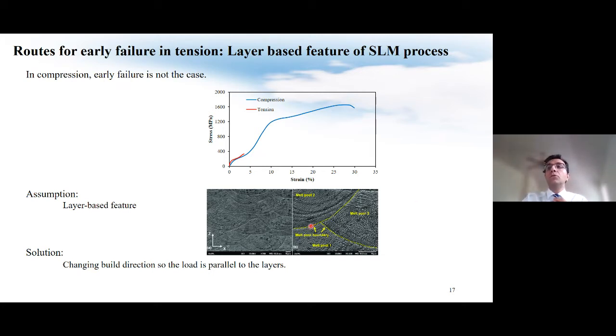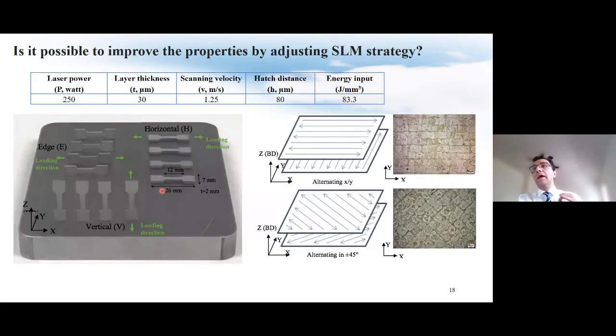Therefore, we decided to study the influence of building orientation and scan strategy with the aim of minimizing the adverse influence of layer-wise fabrication. To this aim, we first fabricated NiTi samples using different build orientations, as you can see here, as well as different scanning strategies. In the figure presented on the left, you can see the building orientations we considered in this study. For the vertical samples, the load direction as shown was supposed to be perpendicular to each layer. However, for the horizontal specimen, the load direction was considered to be parallel to each layer. In the figure presented on the right, the two employed scanning strategies are also presented.